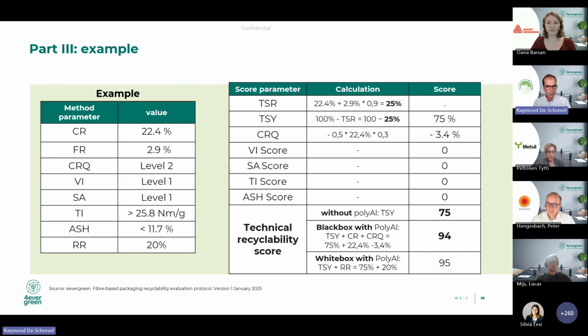Same for the ash. If you are below the 11.7, okay. And here you see this white box parameter, the recyclable rejects. It's 20%. So where you measure 22.4, you would expect 20%, meaning this 20% is the expected amount after an infinite time of using your disintegrator. Then the outcome, there are three possibilities.